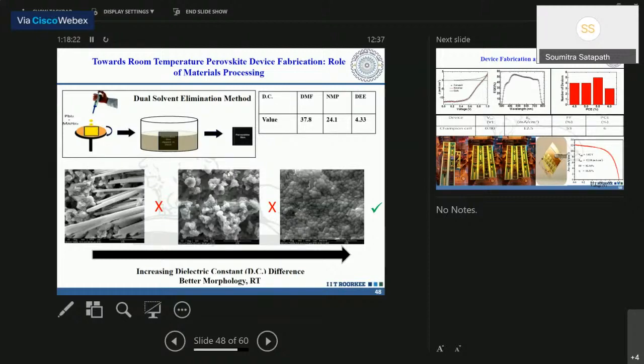When you see the image, the first image belongs to the perovskite film which has been made outside the glove box in an ambient condition in Roorkee, with a temperature of 35 degrees centigrade and humidity of 85%. A very bad thing for a solar cell. Nobody will want to make it, but we tried to give a solution. And you see there is a very bad morphology. If you want to make a solar cell out of it, you will get no efficiency for sure.